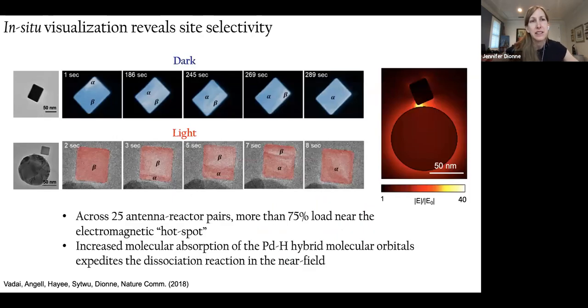And then, of course, since we have the ability to visualize in situ how hydrogen is intercalating, we can see how upon illumination, and in particular how excitation of plasmonic hotspots that are concentrated at the gap between the antenna and the reactor influence site selectivity. So in the dark, when you look across more than 25 antenna reactor pairs, there's an arbitrary corner at which you're going to have the nucleation of that alpha phase. But once you turn the light on, and when you're on the plasmon resonance, more than 75% of those antenna reactor pairs load near the electromagnetic hotspot. So namely near the tip that's closest to the antenna.